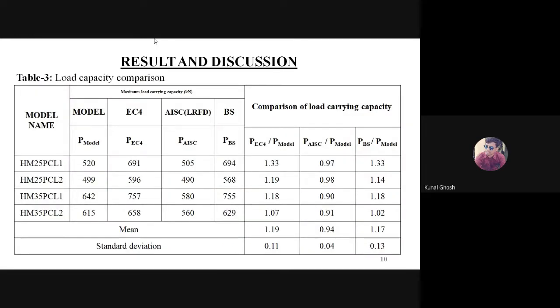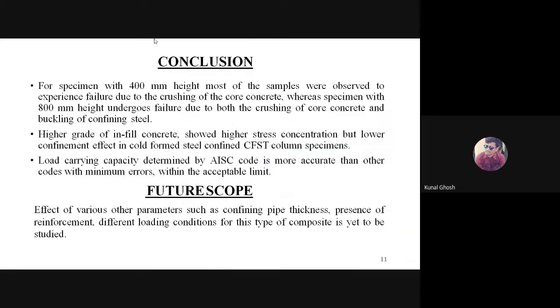In this slide, I will represent the load carrying capacity compared with standard codes. The load carrying capacity for every code and concrete model is presented here, and we can see that the standard deviation in the AISC code is much lower compared to other codes. So the AISC code is much more acceptable than other codes here.